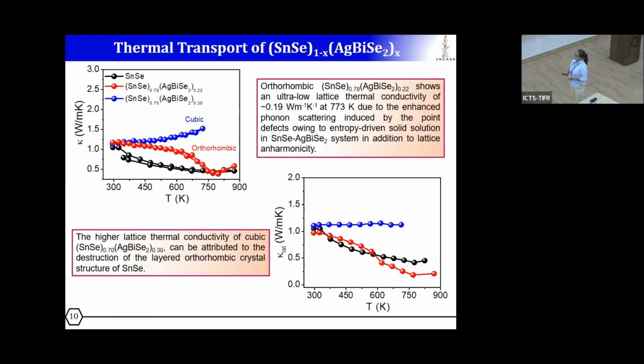Further, when I measured the thermal properties, we have seen this orthorhombic AgBiSe2 alloyed system shows a very low lattice thermal conductivity of 0.19 watt per meter Kelvin at 773 Kelvin, which can be attributed to the enhanced phonon scattering due to the point defects and solid solution of SnSe-AgBiSe2. This upturn around 773 Kelvin denotes the phase transition of SnSe from Pnma to Cmcm.